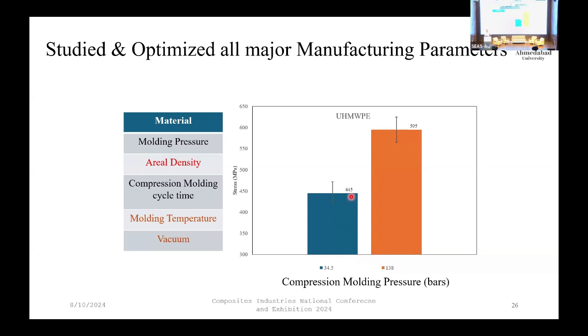So basically I have, let's say, 10 layers of a material. Earlier that was pressed at 34.5. In another specimen, another cycle, it was pressed at 4 times the pressure, that is 138 megapascal. And we observed that the strength has increased from almost 450 to nearly 600 megapascal.